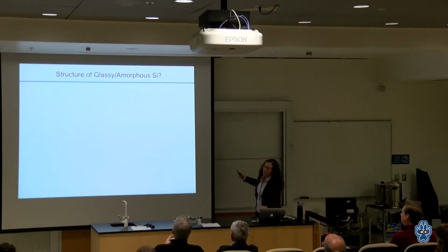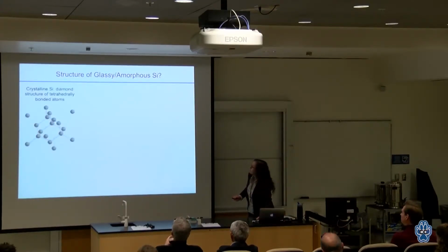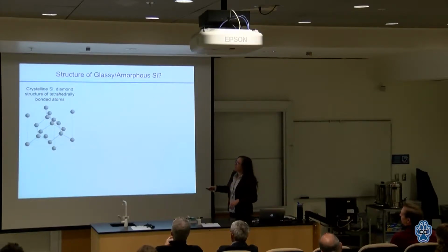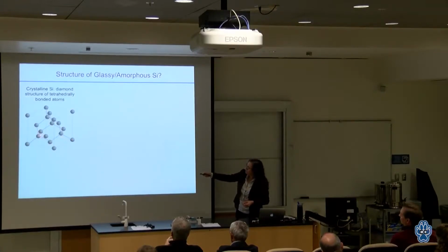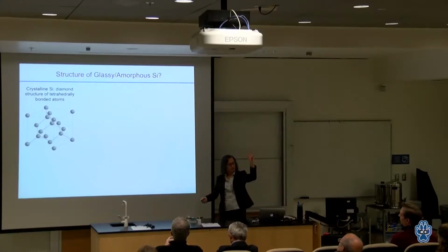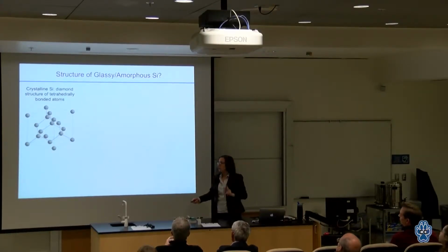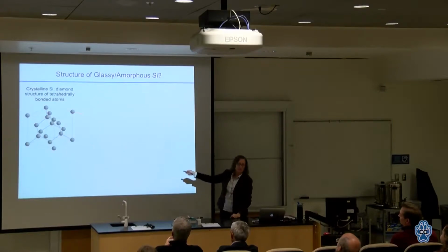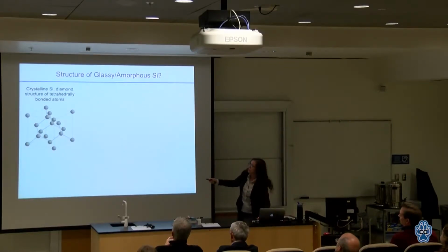All right, so I'm going to talk a fair amount today about silicon. So let me show you what silicon looks like. There is the crystalline silicon. Crystalline silicon makes a diamond structure, just like carbon does. And in that structure, if you look at one atom, it has four neighbors, four little bonds. It's a little tetrahedron, 109.5 degrees between each of those bonds.